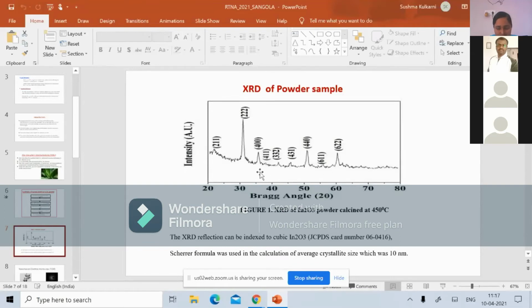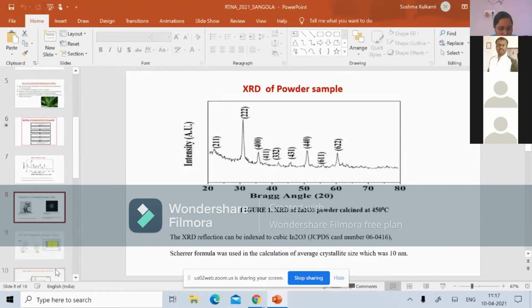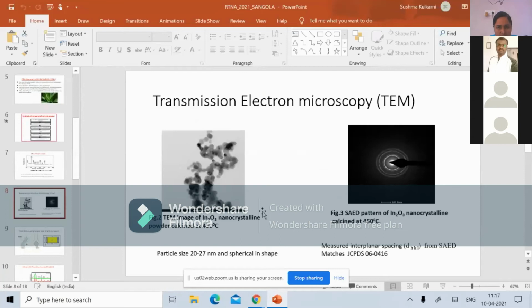The crystallite size can be known from the XRD of the powder sample. Then I have taken the transmission electron microscopy, that is TEM, for morphological study, and here we get a spherical morphology. In the SAED pattern, we find clear rings, and from this it is known that this is a completely crystalline material, and it shows the HKL 222, the major interplanar spacing. From this SAED pattern, it matches completely with the JCPDS card 060416.